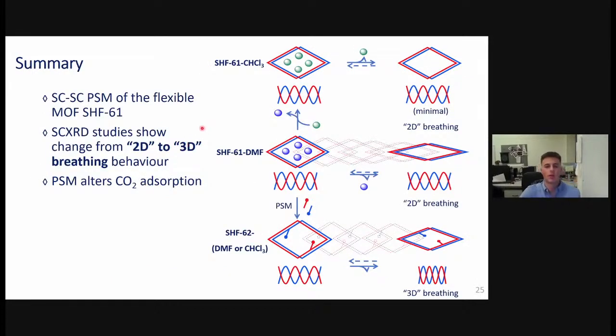I'd just like to finish my talk by quickly summarizing. We've shown that we can do a single crystal to single crystal post-synthetic modification of our quite unusual flexible material, Shef61. And the ability of this modification to go in a single crystal manner allows us to map the changes in flexibility due to that modification. Overall, we've gone from something that breathes in 2 dimensions to something that now breathes in 3 dimensions. So changes in the pore width and the pore length, but also a compression of this helical-like arrangement, which we didn't see before. And finally, we were able to show that this post-synthetic modification actually alters the CO2 adsorption properties of the framework as well. And we've mapped these changes during gas absorption using some in situ studies.